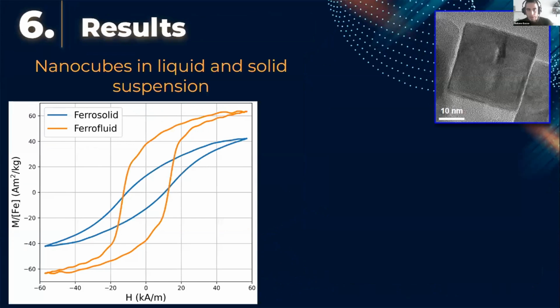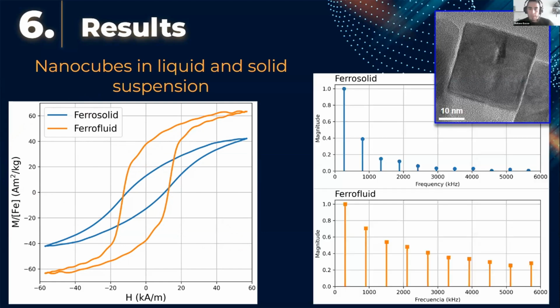So here are some of our results. During our research, we successfully measured radiofrequency magnetic cycles of magnetite nanocubes in different carrier media: aqueous-based liquid suspension and an epoxy resin solid suspension, where we can see big differences in the frequency spectrum. Again, the information which is relevant for us, the specific absorption rate and the relaxation time, is in the first harmonic of the signal.